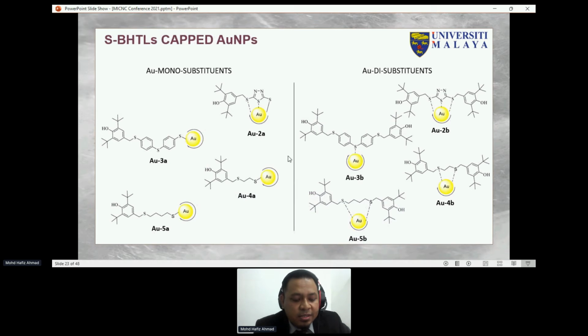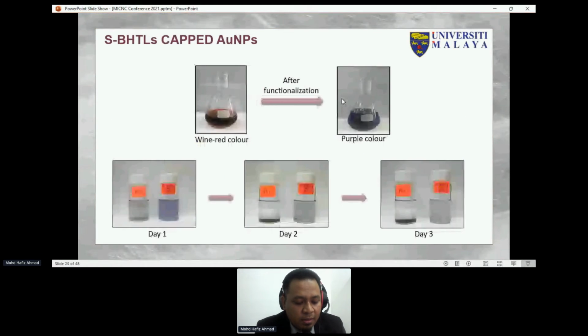Okay, next. Here, 8 new nanocomposites were synthesized to increase antioxidant activity and cytotoxicity effect by the assembly of antioxidant ligands linked on gold nanoparticles. This is the illustration structure of my nanocomposite. Several tests were used to indicate that the functionalization of ligands on the gold surface is successful. First, the color change. As we can see here, the color of the gold nanoparticles changed from wine red to purple after functionalization. It shows that the interaction between ligands and gold nanoparticles occurs. For stability tests, nanocomposites show good stability compared to gold nanoparticles after 3 days.